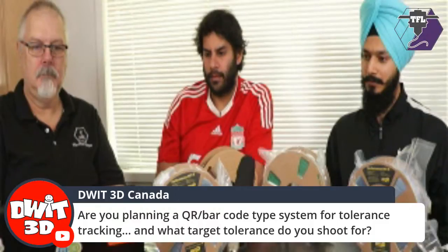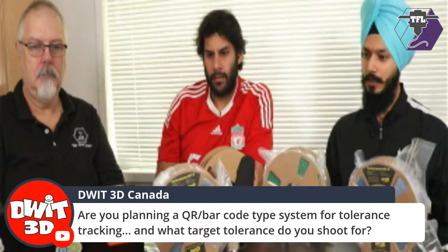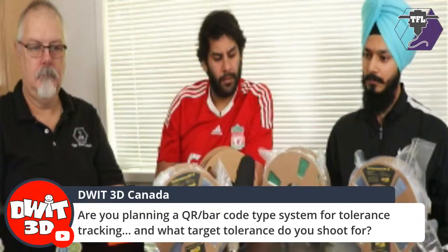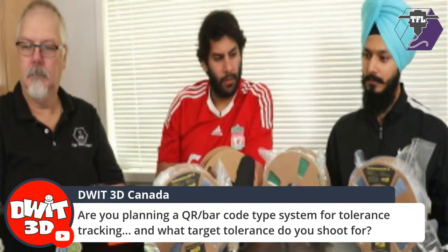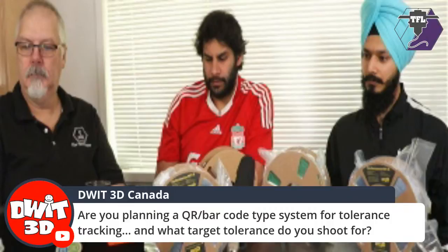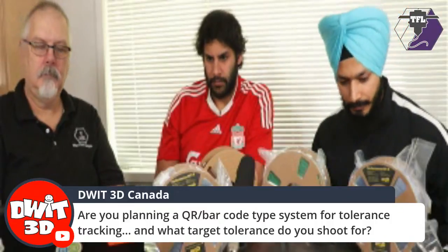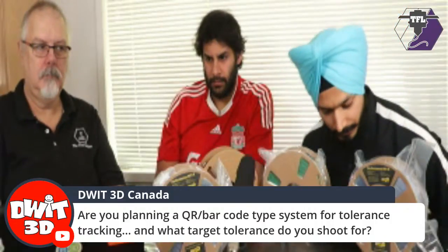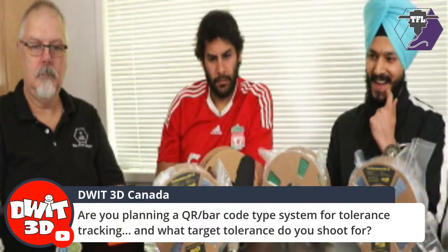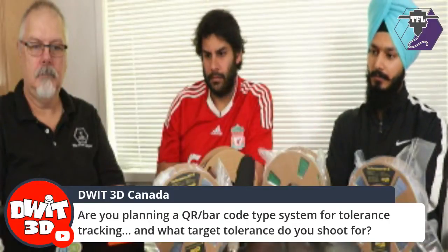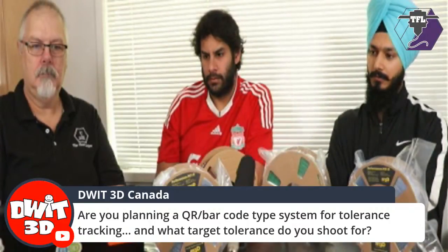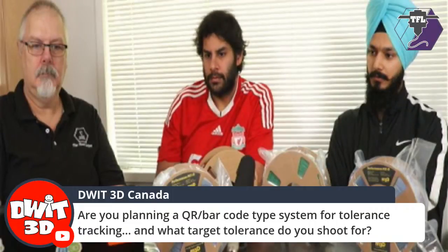And if you have lots of major oscillations in that reel, although it'll feed through the machine, it's going to try and push different amounts through your extruder as it prints, which results in an uneven, dirty surface, which may appear as layer skips or as blobbing. And it's very hard to diagnose at times, especially if you've had a lot of mods on your printer and factors to rule out. So having that 0.02 coming off these reels is excellent, and soon enough you'll be able to go and load up a chart to visually see, hey, my whole reel is going to be this consistent, and when it comes to printing your big prints, you want that consistency.